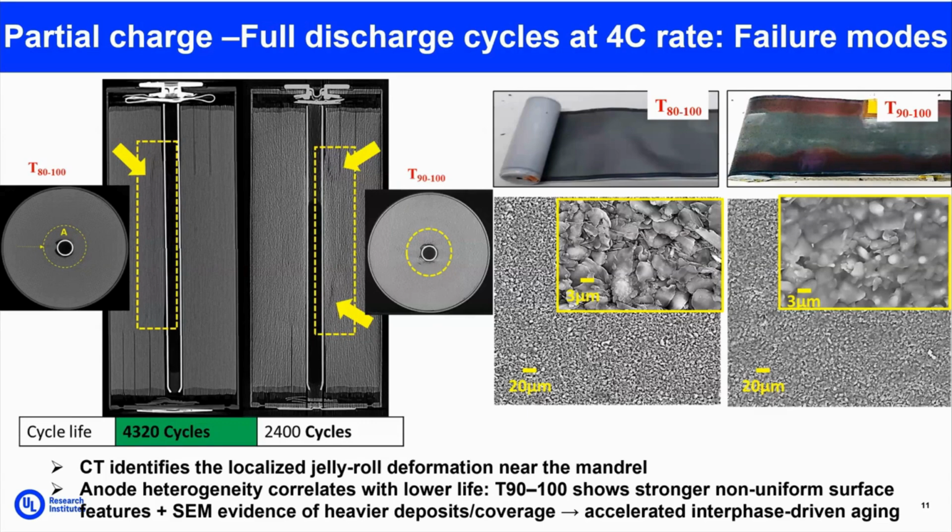Surprisingly, as in the previous case, 100 SOC, 90 DOD, we looked at how the anode surface was. Here also, in the 90 and 100 combination, the aging mechanism on the anode side is similar. Towards the tab sides, the active graphite phases were there, whereas in the middle portion the lithium deposition and plating concentration is very high.